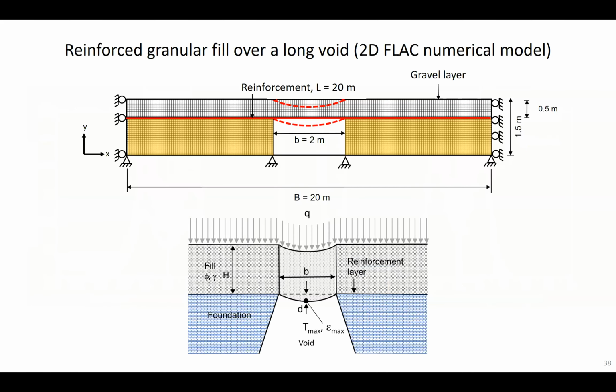Now, returning again to this reinforced granular fill over a long void, the problem with these analytical solutions, which are captured by this diagram that you see at the bottom of the slide, is they're very simplistic models. They really can't truly capture the interaction between the soil, the reinforcement, and the like, because these are coupled problems. The only way that you can gain insight in this regard, at least numerically, is to carry out numerical modeling with, for example, say FLAC. FLAC happens to be our favorite program.